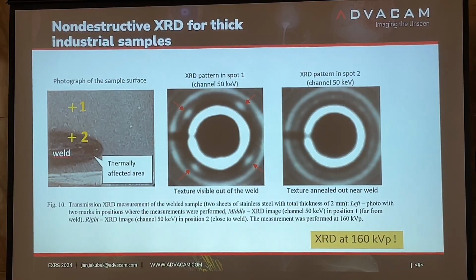But if you go closer to the weld, where the area was heated up, and then it recrystallized again, but it recrystallized homogeneously. So this orientation, this texture disappeared completely, and we see that it is isotropically distributed again. So you basically lose certain material properties because of the welding. So that's something you can do, going across the full thickness of the sample.